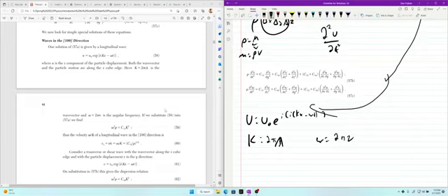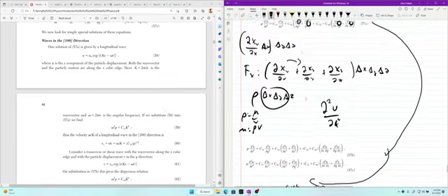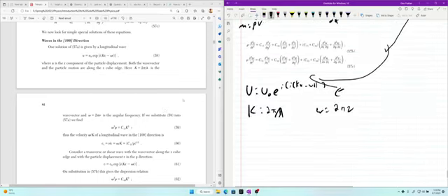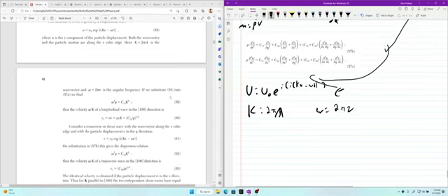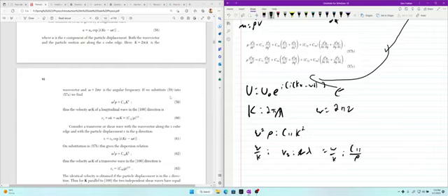If we substitute 58 into 57, 58 being this, and 57a being this equation right here, we find that omega squared rho is equal to C11 k squared. Thus the velocity, frequency over wave vector, omega over k, in the 1, 0, 0 direction is given by v_s equals nu lambda, which is omega over k, which is C11 over rho to the 1/2.